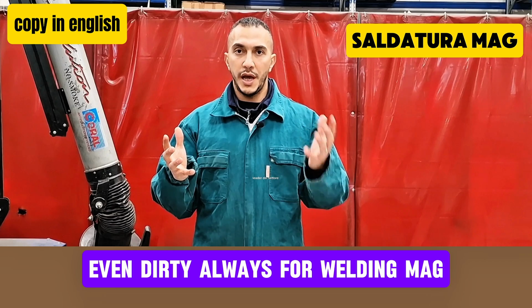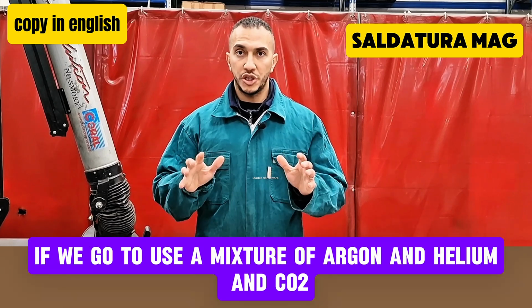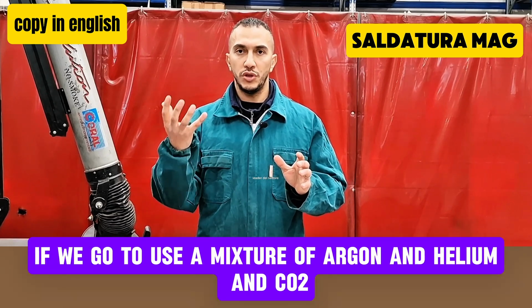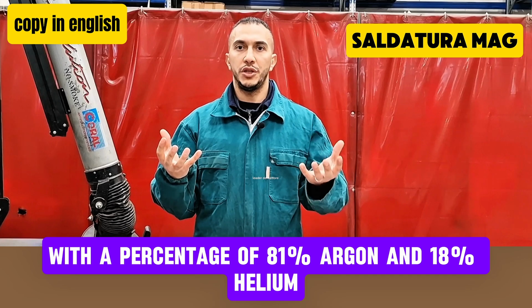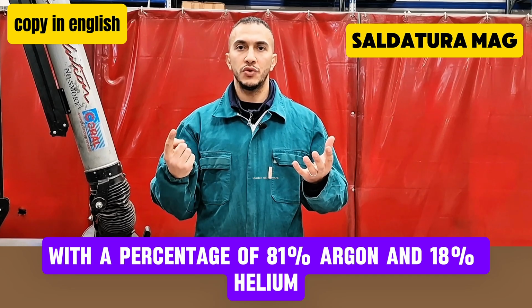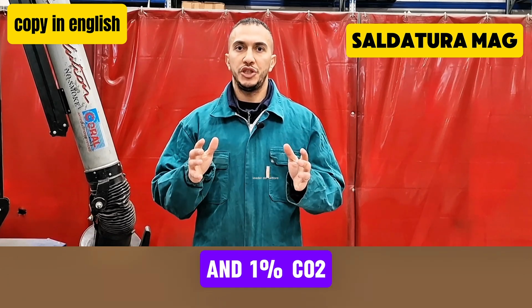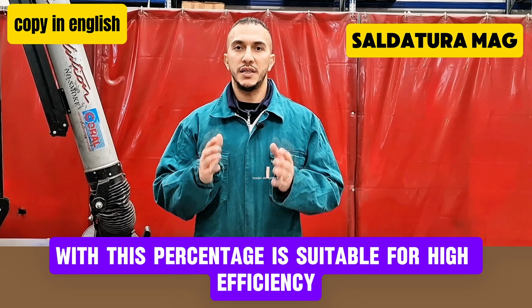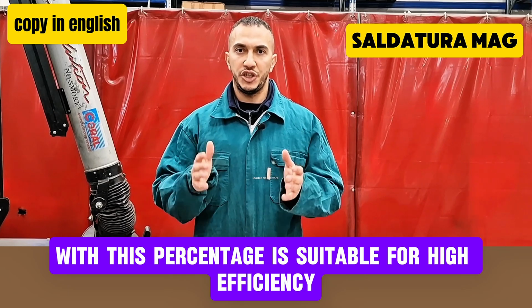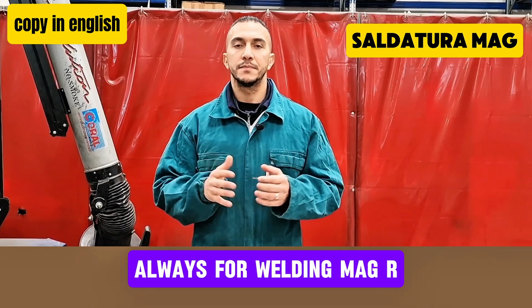If we use a mixture of argon, helium and CO2 with a percentage of 81% argon, 18% helium and 1% CO2, this type of mixture is suitable for high efficiency MAG welding of stainless steel, always for MAG welding.